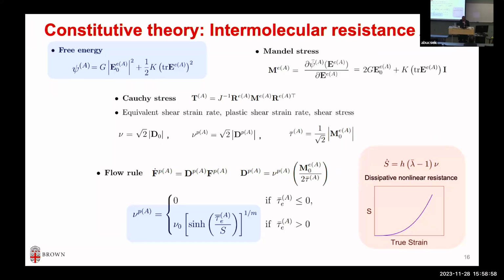So for mechanism A, again, we have done this when I was a PhD student, most like standard viscoelasticity. First mechanism, you can model elasticity using a three-dimensional linear elastic behavior. For the viscous part, we can use rate-dependent viscosity, plastic strain rate as a function of stress, with or without temperature dependence. We have done this in the past, we've taken that first mechanism.